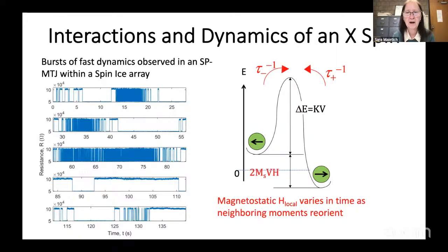But first, I want to say a little bit more about what we see from the experimental data. Starting with the X devices, when you make spin ice, you're expecting the dynamics to be different because of the magnetostatic interactions. And if you look at a long time, not microseconds, but seconds, hundreds of seconds, you see that the same device will telegraph, slow down, speed up, slow down, speed up, slow down, etc. And it has periods where nothing happens for 10 seconds, just stays in a particular state.